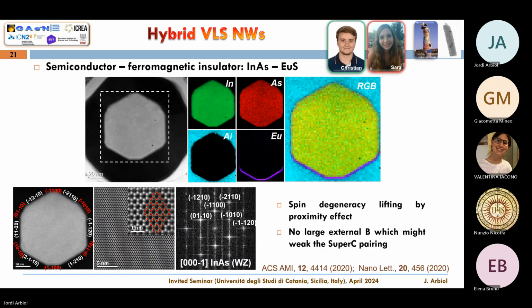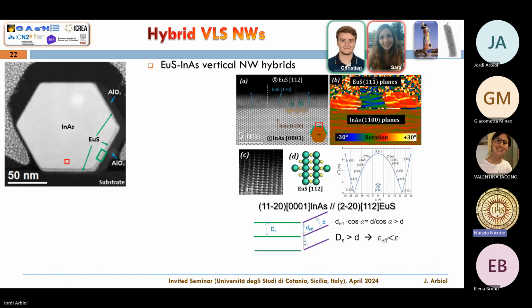But there is more. With these materials, you need to use super high magnetic fields. A way to get rid of this is by using a ferromagnetic insulator between the semiconductor and the superconductor. And this is a way to lift the spin degeneracy, but not using these large external magnetic fields, okay? Because then you could weaken the superconducting pairing. But the thing is, we were thinking about europium sulfide, which is a nice ferromagnetic insulator, but then you take into account the indium arsenide. It looks like this hexagonal shape. This is the cross section.